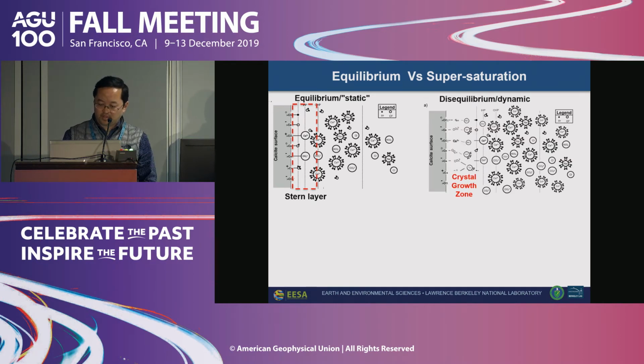disequilibrium, or particularly supersaturation condition, you have the active growth of the mineral. So there are actually ions that are rushing to the surface to form crystals. You likely have this, what we are thinking is the extended stern layer. Basically, you have a much thicker stern layer and potentially much higher charge density at this interface. This actually is linked to the signal we think that we're observing.